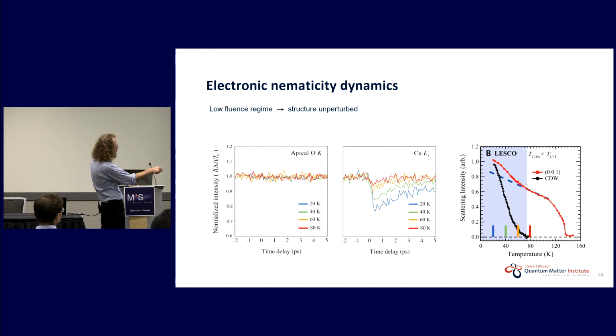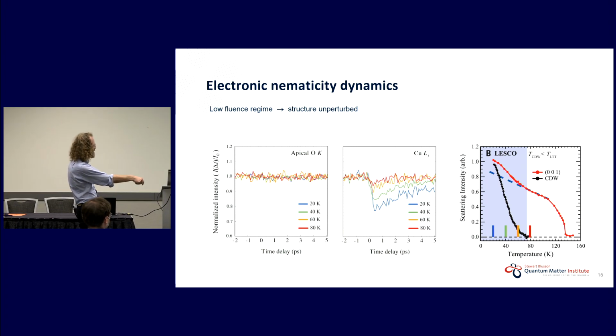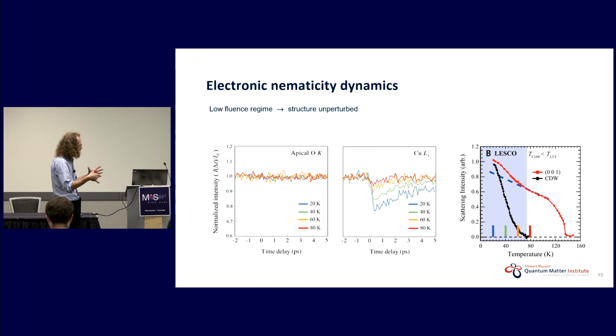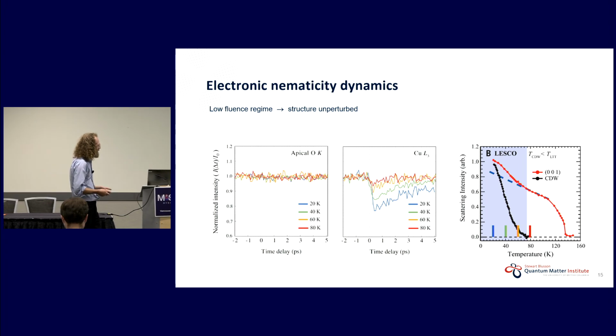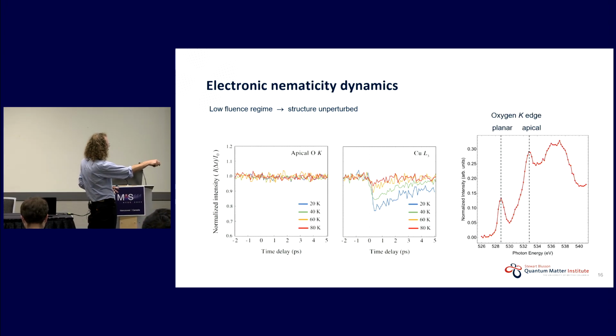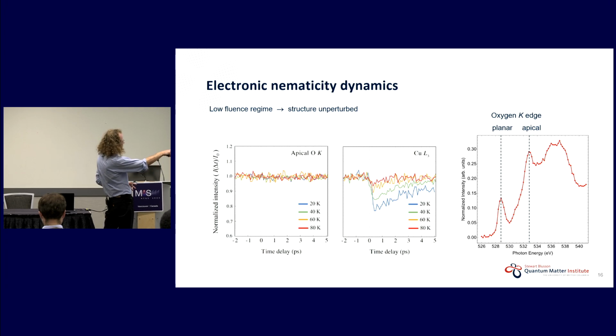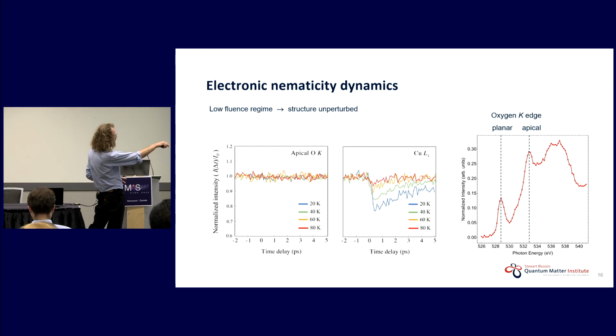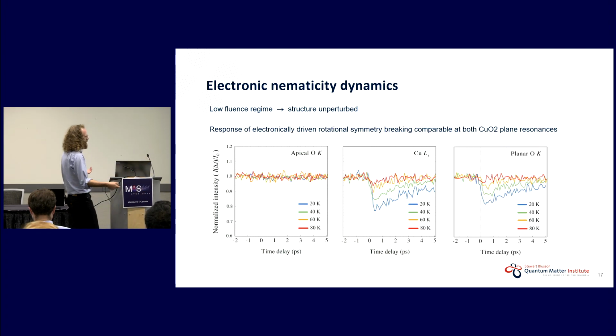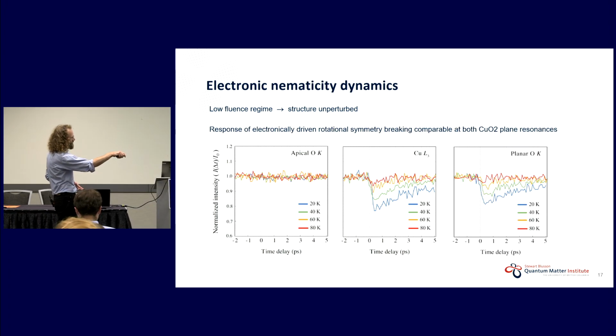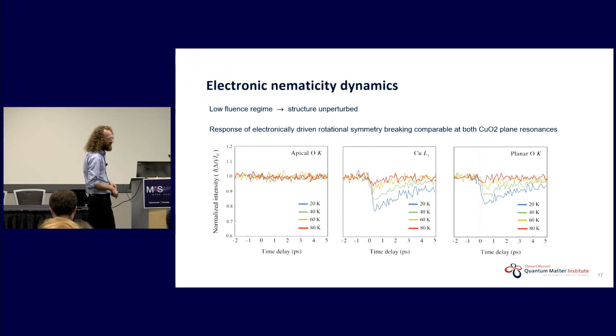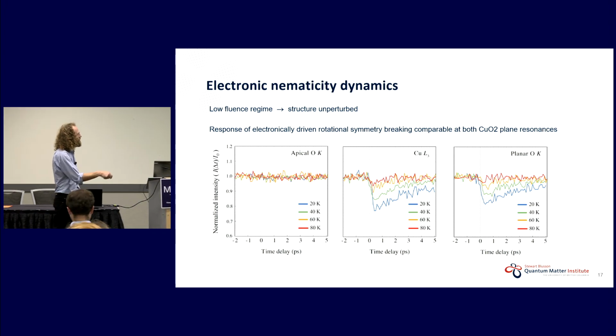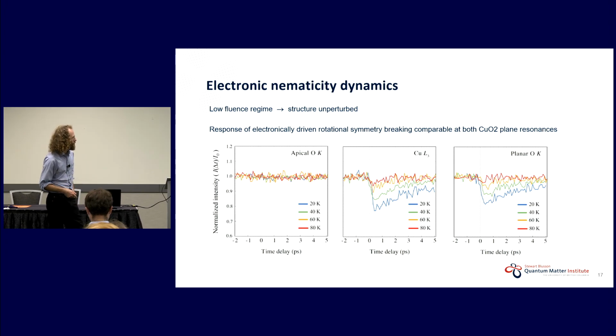And now you can also ask, well, the copper L3 edge, that's 930 eV. It's almost 400 eV away from the oxygen resonance. Maybe there's something more complicated going on. So then we say, well, okay, we're going to test that by moving to the planar oxygen. This is the oxygen K edge, and you have a feature here associated with the planar oxygens, and then at higher energies, the one with apical. We move between the two, and what we find is, at the planar oxygen K resonance, you have a behavior which mirrors what happens at the copper L3 edge. So this gives us strong confidence that here we're looking essentially at the physics of the copper O2 plane.